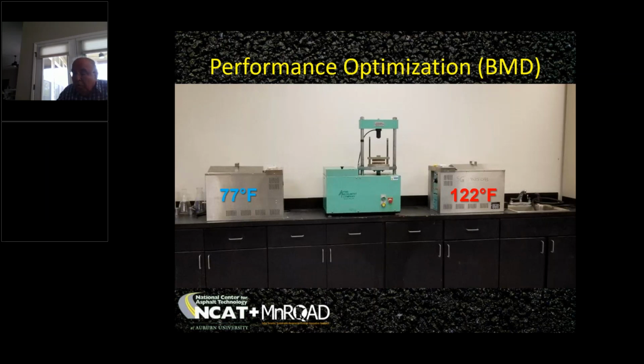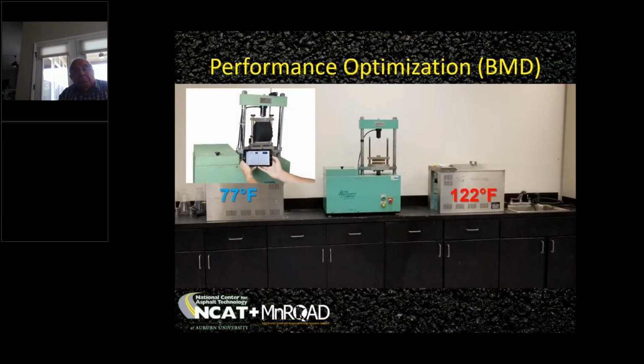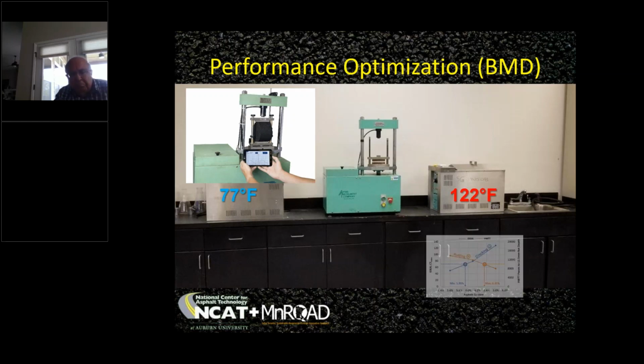Well, we can break pills at a medium temperature, 77 degrees Fahrenheit, and a hot temperature here, 122 Fahrenheit. And we can use the cooler samples to assess cracking performance or ductility of the mix. And then we can use the hotter sample to assess the rutting performance of the mix. Now you can do a manual analysis of the old plots if you've got one of these devices, but now there are smart jigs you can put inside these machines and do automatic data collection. And the idea with this is that we can balance rutting and cracking and use the relationship between those two performance parameters to optimize the amount of asphalt that we put in our mix.